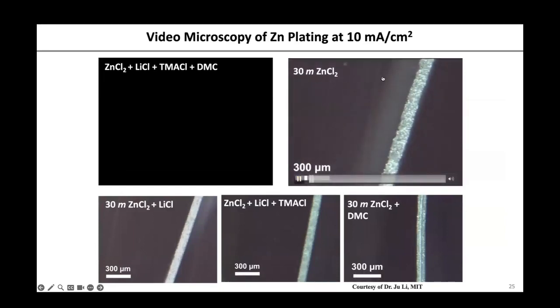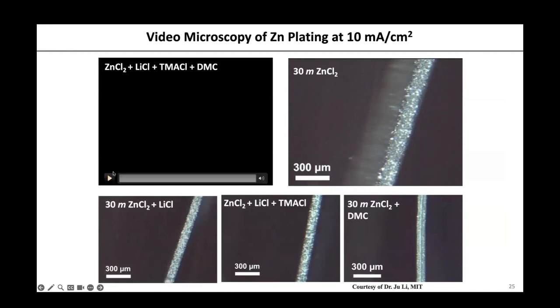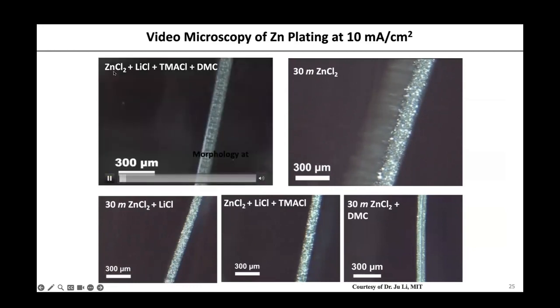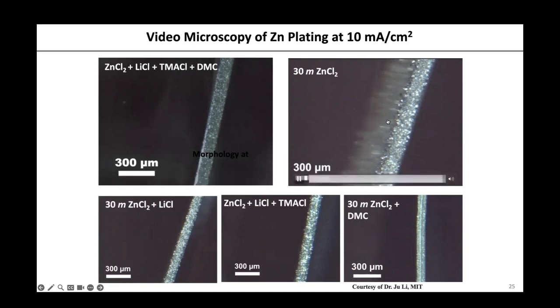This is the pure zinc chloride. You see the bubbles coming out from the electrolyte reacting with zinc, and the surface is quite roughened. But if you have lithium chloride added, that helps. And with further TMACl added, that looks good too, but you can still see asperities on the surface. But if you have our final recipe with everything added plus DMC, this is the surface. It's not going to produce dendrites or whiskers or irregular morphology. It's very, very flat. Look at the contrast between these two electrolytes.